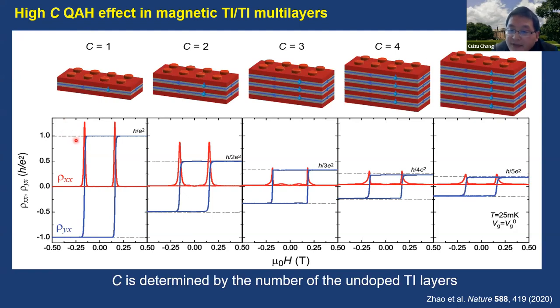Let's take a look at the transport data. We can see that in this sample, the Hall resistance at zero, this is the magnetic field dependence of the Hall resistance and longitudinal resistance. And in this sandwich layer, because there is only one undoped TI layer, it's quantized at h over e square. Here is h over 2 e square, here is h over 3 e square, and up to h over 5 e square. We can see that the zero magnetic field Hall resistance is determined by how many undoped TI layers are in these samples. And from this transport result, we can see we realized quantum anomalous Hall insulators with Chern numbers from 1 to 5.